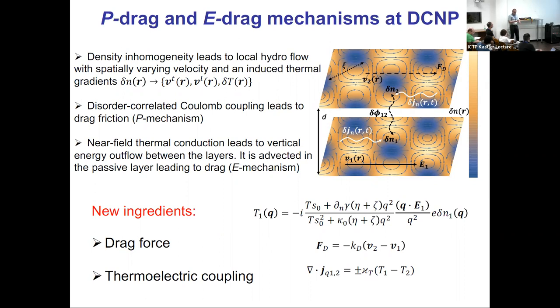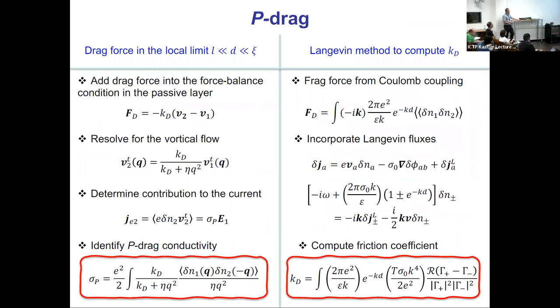And so they can be incorporated together. It gets a little messy, but maybe I'll just flash some results. You could derive an expression for the P drag component, the momentum mechanism of drag resistance. It has a very similar form to the conductivity enhancement near charge neutrality that I showed you earlier. It contains the correlator of density fluctuations in each of the layers, and it scales inversely proportional to the fluid viscosity. It contains this drag coefficient that needs to be calculated. It's a little work to do this, but it's doable. It actually goes a little beyond the pure hydrodynamic picture. You need to promote hydrodynamics to include Langevin fluxes and work with that.